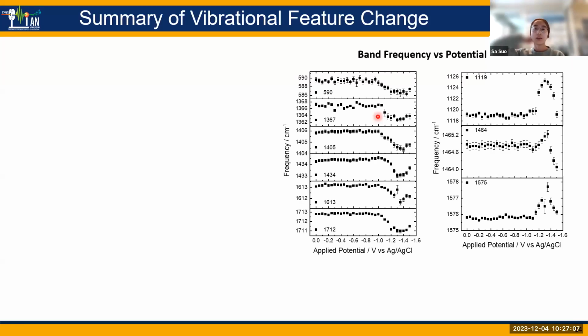Okay. So if we dig into the frequency trend, we basically see a group of peaks showing redshift, and the other three peaks showing blue shift. Normally the shift in these Raman bands could be due to the electron density change of the corresponding vibrations. For example, increasing bond length will give rise to a smaller frequency due to a smaller oscillator strength. So that's our hypothesis.